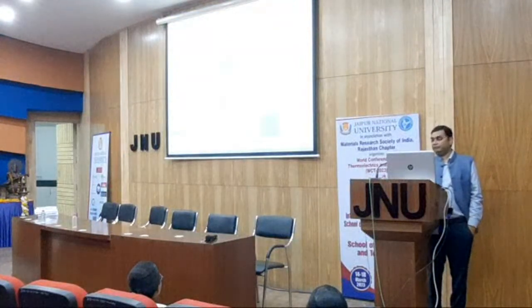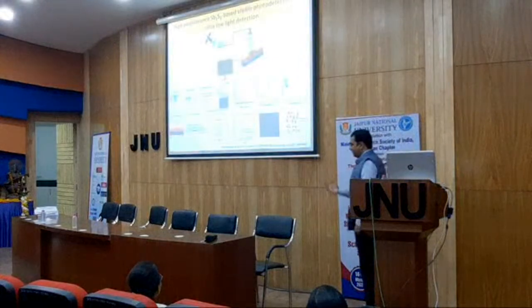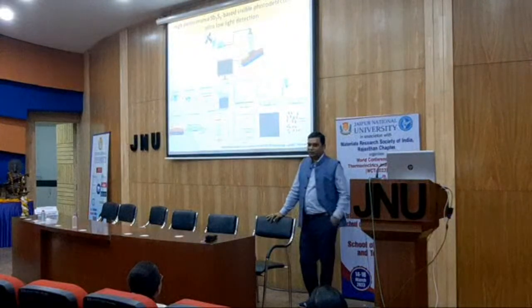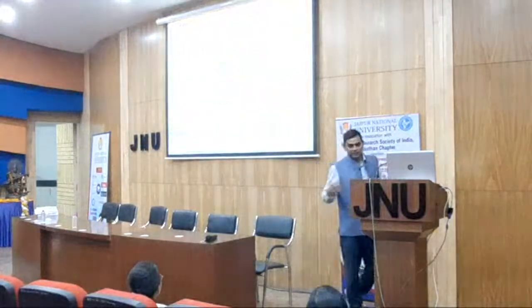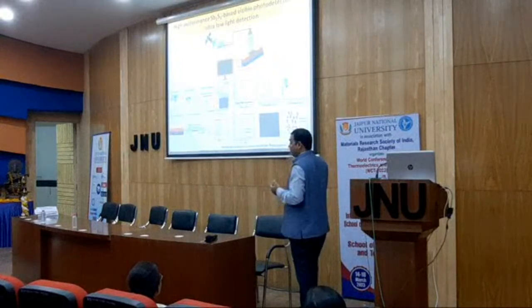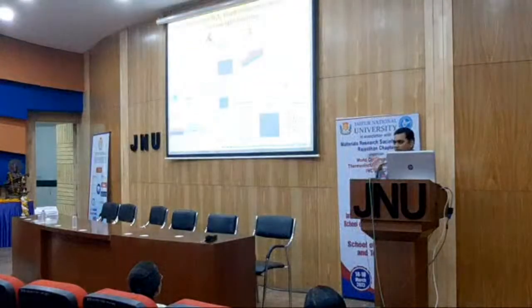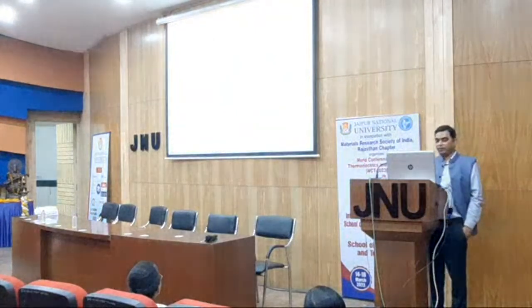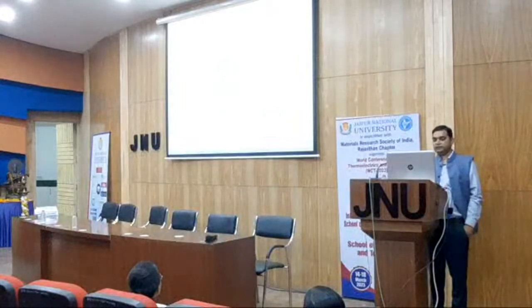The new one is because when I used to give a presentation, many people used to ask, you are growing on a 15 crore machine. Why don't you grow with a lower cost machine? Why don't you try with the thermal evaporation method, which costs you a few lakh rupees? So we have tried with thermal evaporation. We have to choose a material which can be evaporated by thermal and can be of very high quality. So we have utilized this Sb2Se3 material with the thermal evaporation method, and this is showing enormous performance in the visible range. With this very simple method, we are growing microdots and then finally growing in thermal evaporation. Device stable. I would like to summarize here.